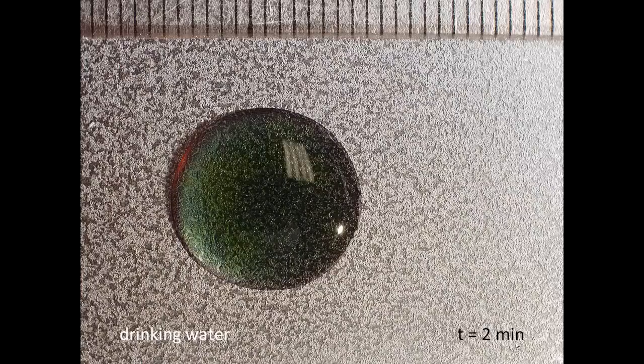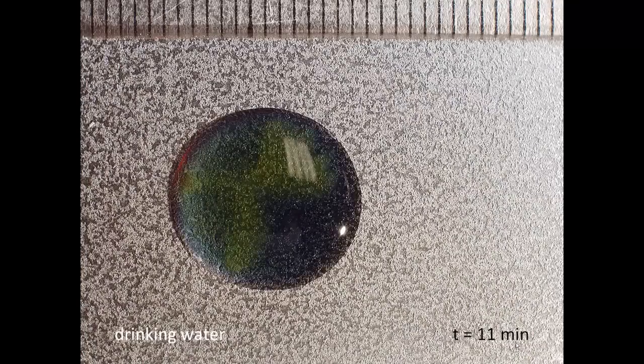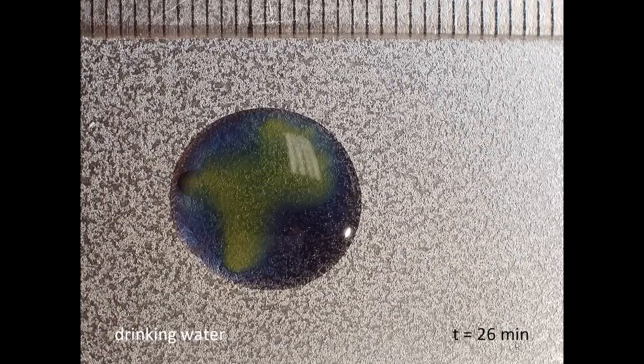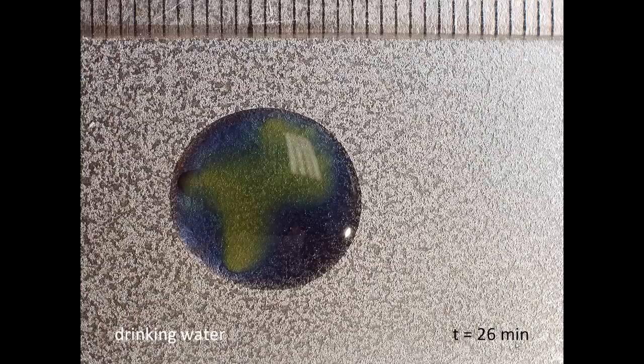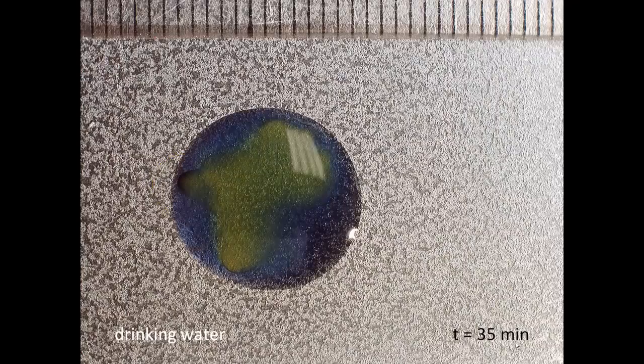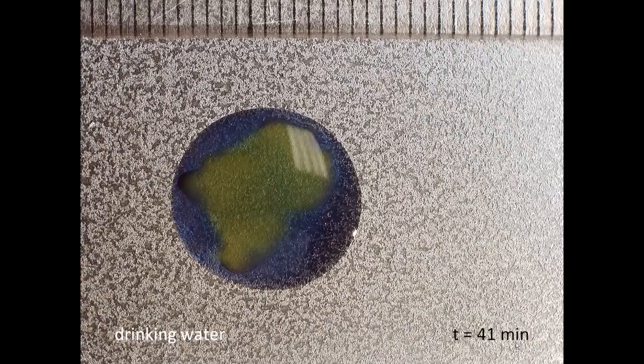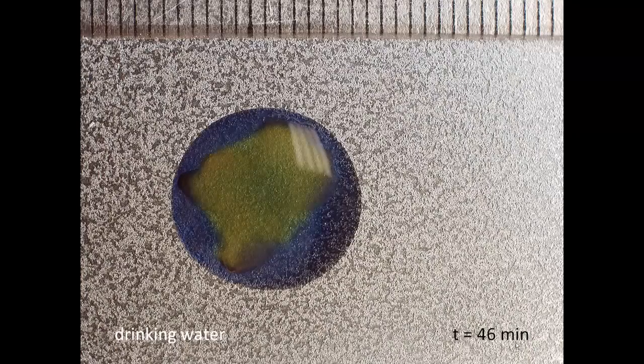Now we're going to fast forward through time. Here's two minutes with a little bit of blue, turning a little bit caustic or basic. Now notice at 11 minutes it begins a little yellow cross there in the center. As time progresses to 26 minutes, it's becoming bluer on the outside with yellow there in the center—it's becoming acidic in the center and basic on the outside rim. Notice it's starting to precipitate some rust right there. Here's 35 minutes, continuing, and 41 minutes, continuing more. The yellow and blue get deeper, so we have two zones going on here.